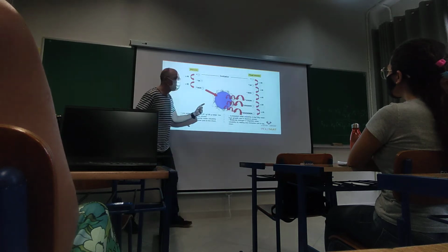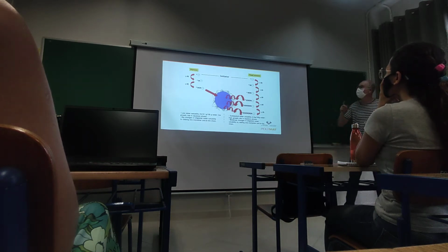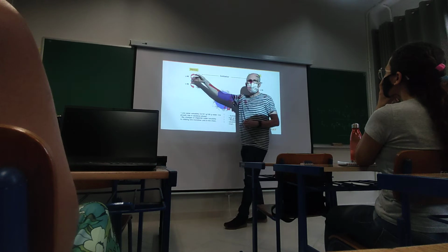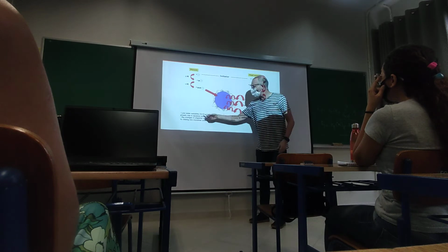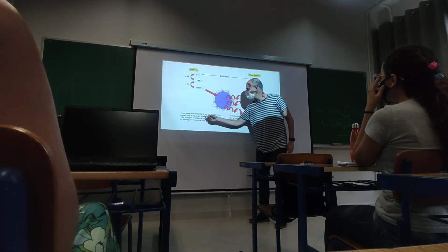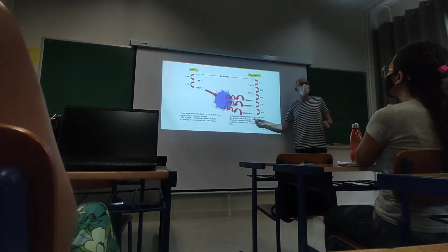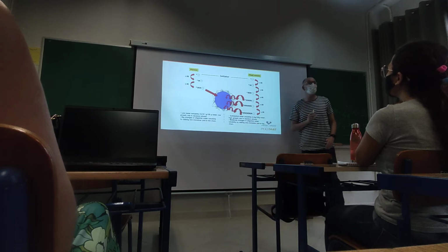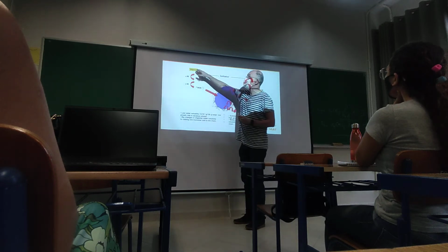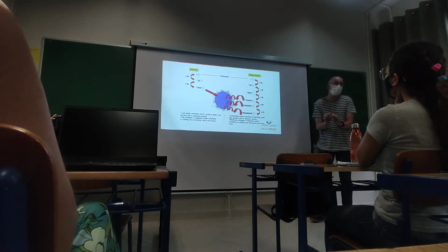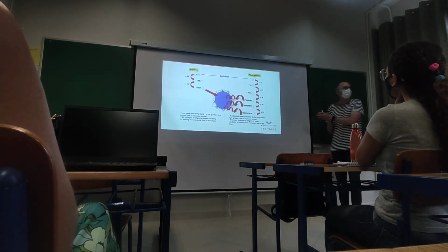Okay. The other aspect that is important for entry is the solubility of the monomer. Here you have two case examples: vinyl acetate and styrene. Styrene monomer has a very low solubility, 10 to the minus 4 grams per 100 grams of water, whereas vinyl acetate has high solubility, 2.5 grams per 100 grams of water. This means that when you are running an emulsion polymerization with styrene, the concentration of styrene in the aqueous phase is very, very low. When you have vinyl acetate, the concentration is much higher because of the solubility.